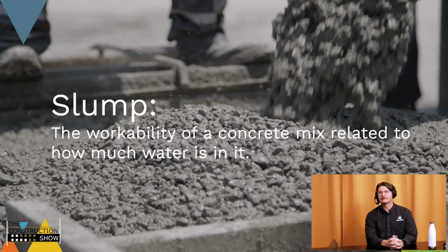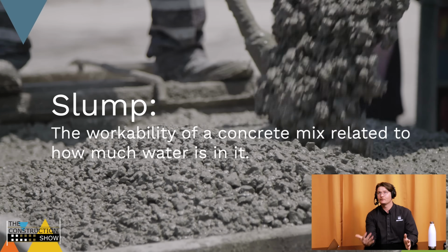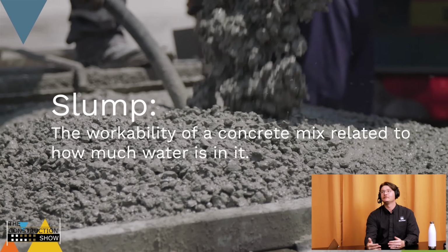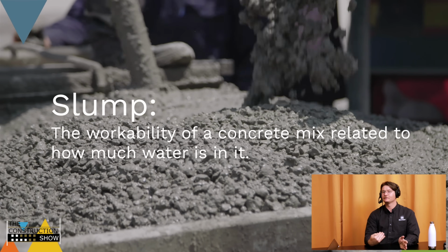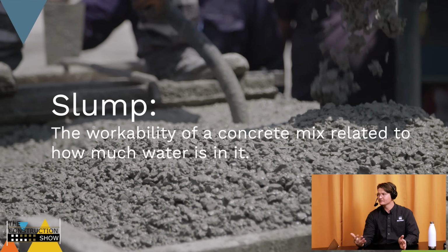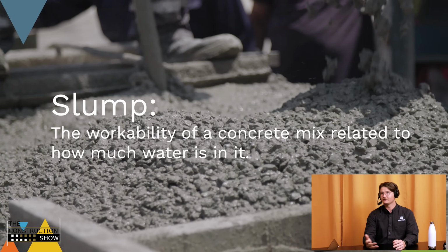A good performing concrete will have a minimal amount of water in it, and that would generate the most durable and the strongest product. But if you don't have enough water, then you don't have a product that the finishers can put into place, and you won't get good particle packing. If it's not flowing, you can't have the aggregates touching each other, and minimizing that void space could be detrimental to the durability and strength of the concrete. So you're always looking for this sort of happy medium.